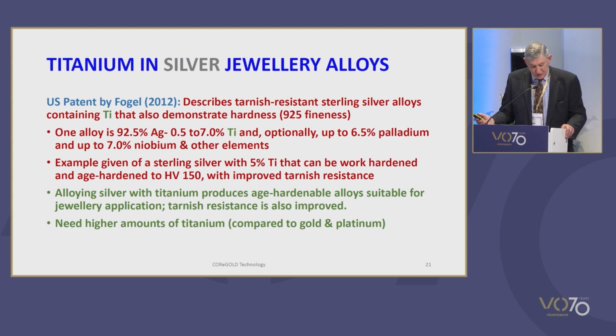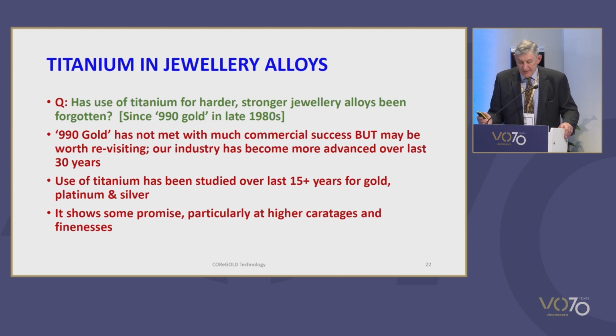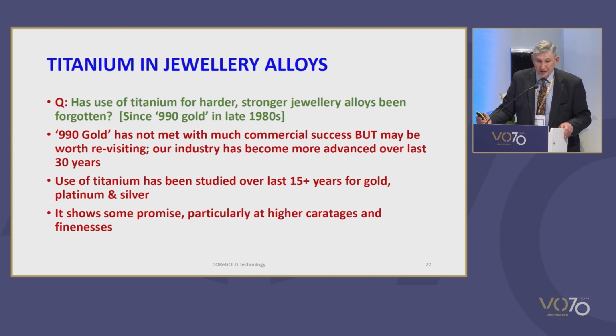From these studies, it can be deduced that the principle of alloying silver with titanium can produce alloys that can be age hardened and would find interest in a jewellery application, especially as tarnish resistance is improved. Higher amounts of titanium than needed for gold and platinum appear to be needed for the reasons I've already discussed. The title of this paper begs the question of whether the use of titanium to produce harder, stronger alloys in precious metals has been forgotten since the development of 990 gold in the late 1980s. This alloy has not met with much commercial success in our industry, but it may be worth revisiting as our industry has become more technically advanced over the last 30 years.